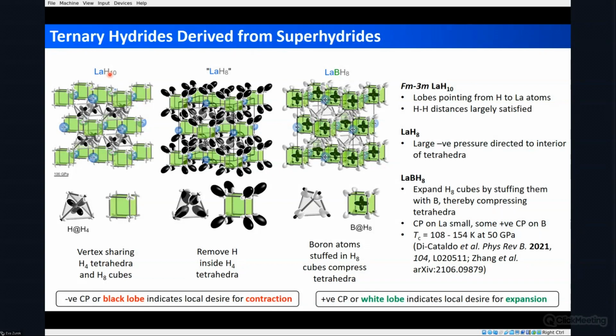So if we start from LaH10, this is another way to visualize it, not as clathrate cages, but as these kinds of cubes that are going to be linked by tetrahedra. So you have vertex sharing H4 tetrahedra and H8 cubes. And if we see the chemical pressure map, we see these types of lobes pointing from the hydrogen to the lanthanum atoms as the most standing out feature. If we then remove the hydrogens inside these H4 tetrahedra, we get really large negative pressures directed inside them.